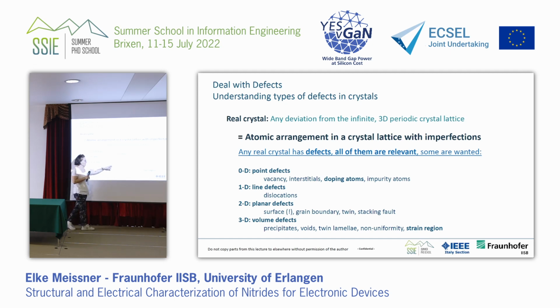Grain boundaries, we may want or not. Twins we don't want, stacking faults we don't want. They can all do odd things in a semiconductor crystal. Volume defects can be precipitates, voids, non-uniformity. A volume defect we also consider a strained region. A strained region is something we want too. So a strained region we want, if we want to create a 2DEG, we want a strained region because otherwise we have no 2DEG. We have HEMT devices, for example. We want strained regions, otherwise it doesn't function.